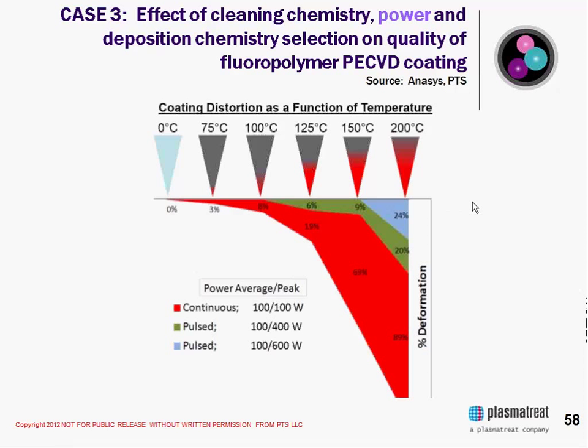And I mentioned that we are continuing this work. We are also confirming the influence of the thickness of the coating and whether or not that's affecting the sensitivity of the Tg measurement. So it's possible that some of the continuous processes, these two processes, were a very thin coating, so the thermal tip just went through the coating rapidly. And this is a thicker coating, so it was more of a coating to permeate. So we'll be presenting some more information at the Adhesion Society next month. And these posters are on our website.